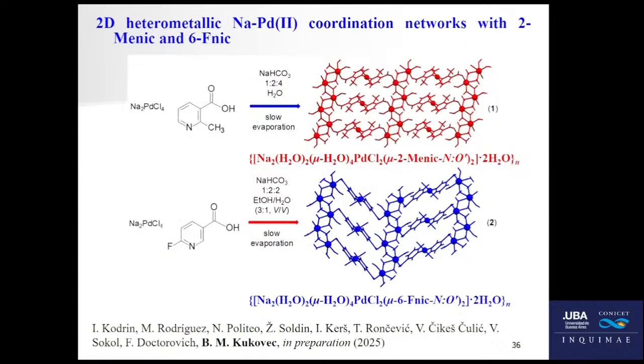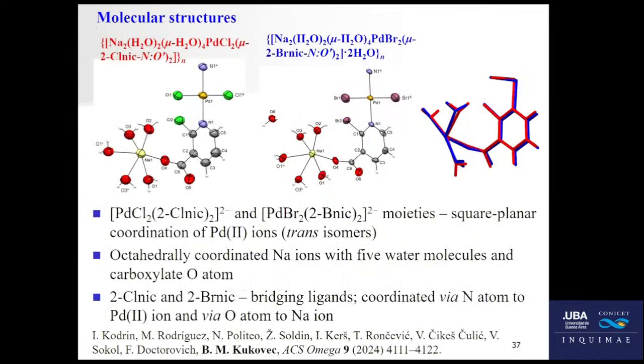Before that, we also used, this is still not published, but currently in preparation, but I included it here. So we also used 2-methylnicotinic acid and 6-fluoronicotinic acid, and very similar experimental conditions. The only difference is that if we use the 6-fluoronicotinic acid, we use a mixture of ethanol and water, and somewhat different ratios of the reactants, but it doesn't matter at this point.